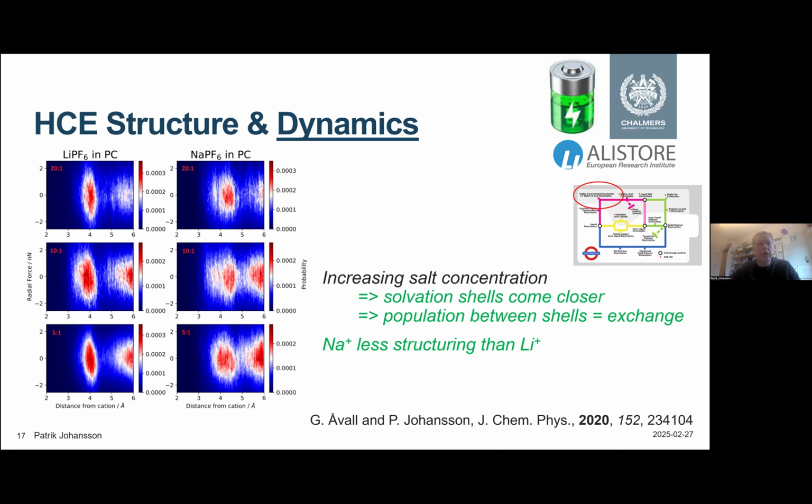But what you can see if you go from top left down on the LiPF6 concentration, one sees that it gets a little bit closer between the solvent shells. The lithium, though, if one compares the leftmost to the one a little bit to the right, one sees that moving from lithium to sodium, it gets not at all as structured as it gets with lithium. Not surprising. Lithium would organize its solvent shell much harder than the sodium will.